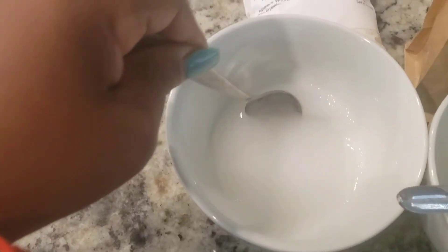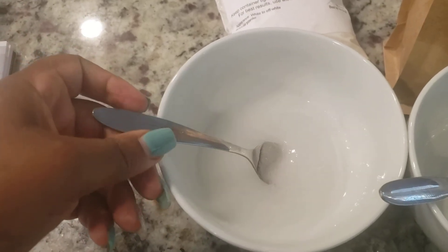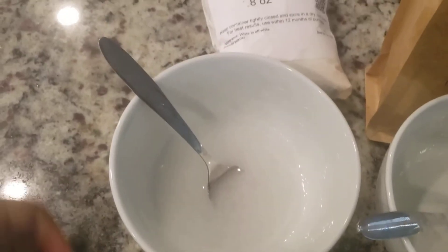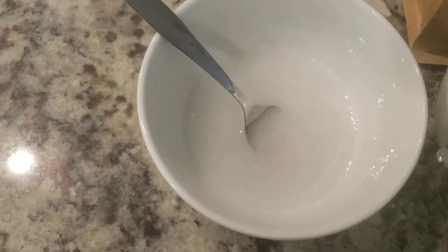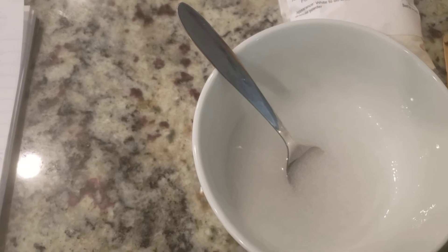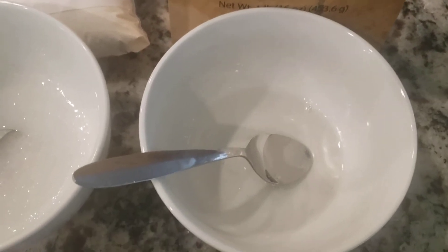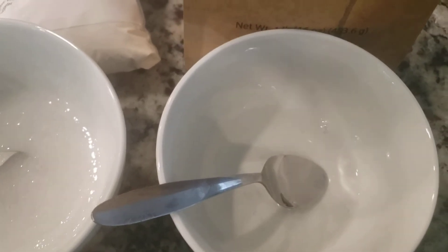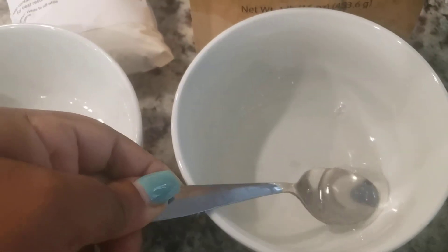I was a little worried last night — I honestly didn't know how long it would take to fully hydrate. Give this hydroxyethylcellulose a few hours. The usage rate for hydroxyethylcellulose is anywhere from 0.5% to 2%, and for methylcellulose it's 0.2% to about 1%, so you're going to use much less of the methylcellulose.